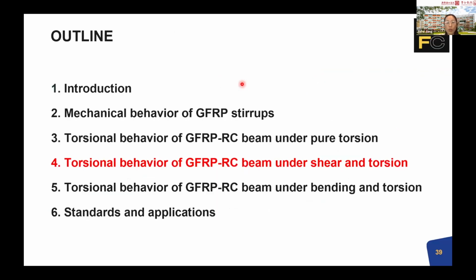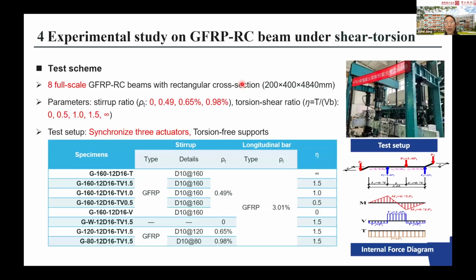Then we come to shear and torsion, where we have done 8 beams with combined shear and torsion. Here also with different stirrup ratios, and here is the torsion to shear ratio from complete shear, to infinity, meaning pure torsion. Here is an illustration of the test setup. We have 3 actuators, which are synchronized by the system. P1 and P2 are for torsion, and for the middle force, P3 controls the shear force, and the ratio between P1 and P2 controls the torsion and shear ratio.